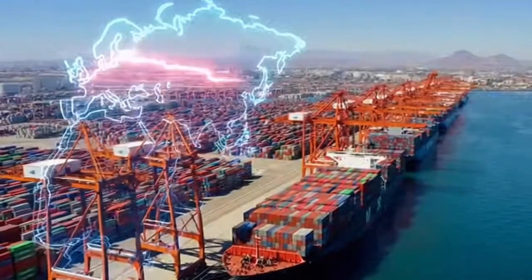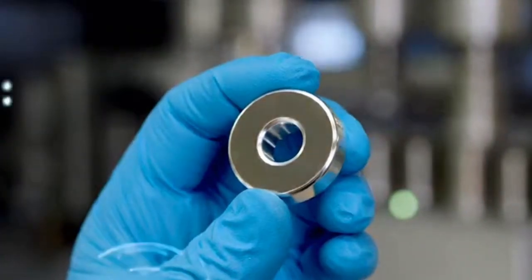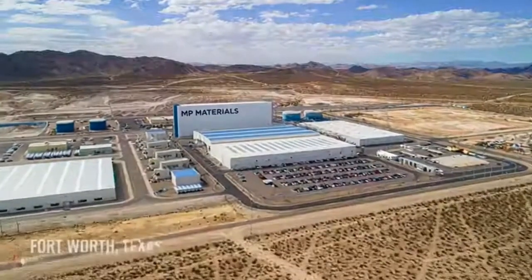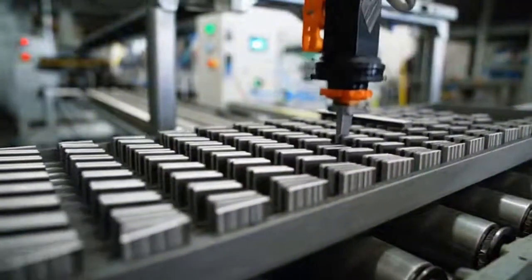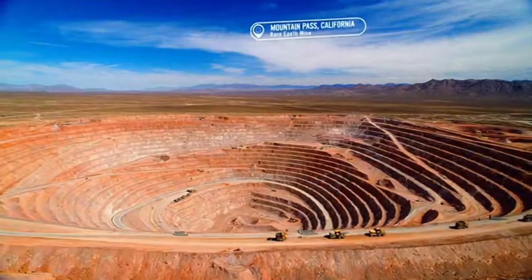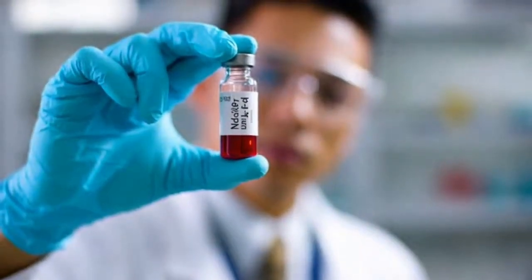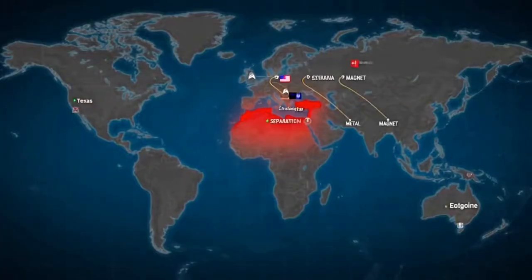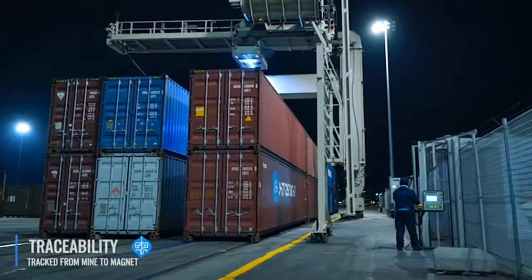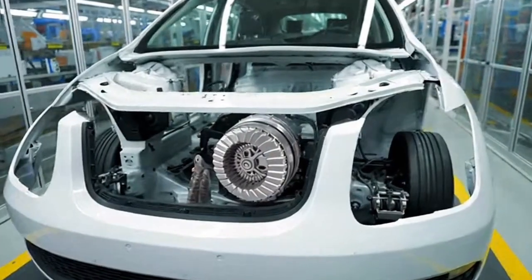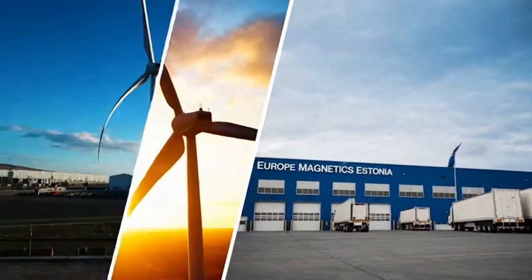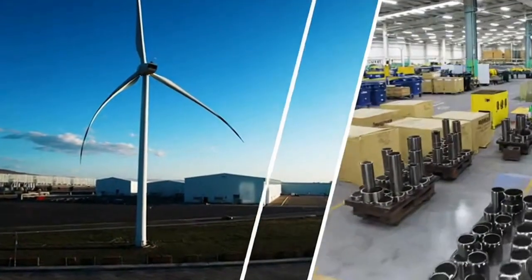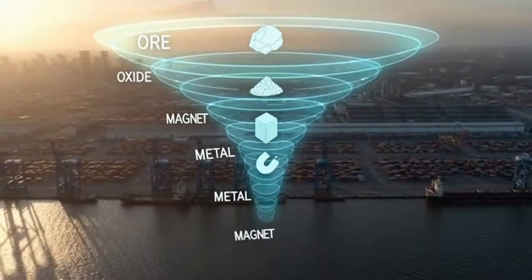And if you want your magnet to perform at high temperature without loading it up with heavy rare earth elements, there's one more trick: grain boundary diffusion. That means wicking a small amount of dysprosium or terbium into the magnet along the grain edges. This puts a tough little shell of high coercivity material around the grains so the magnet's inner strength is protected when things get hot, without penalizing the room temperature performance too much.